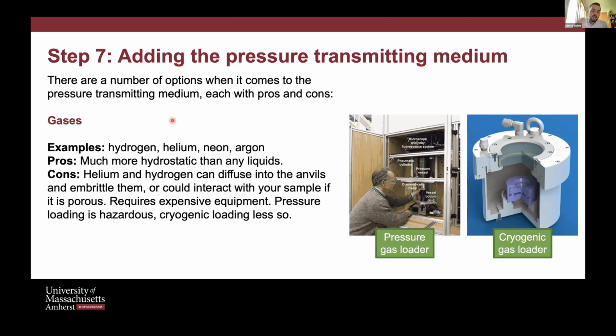So you can imagine a very tall column of water. At the surface, it would be low pressure. The very bottom, under the weight of all the water, it's going to be higher pressure. So it's not the same pressure throughout the entire column of water, but at any point, those forces should be equal. And so that's really what you want for single crystal, because otherwise you get strain. The downside that you should consider is that certain porous systems, if you're looking at MOFs, for example, you can actually be changing the chemistry of what you're looking at, because the pressure medium can actually enter the sample, and that might not be what you want.